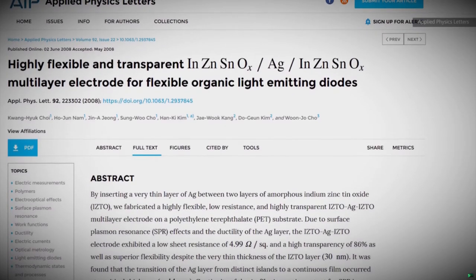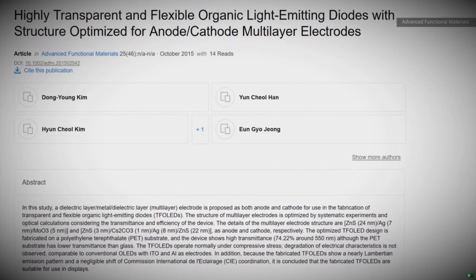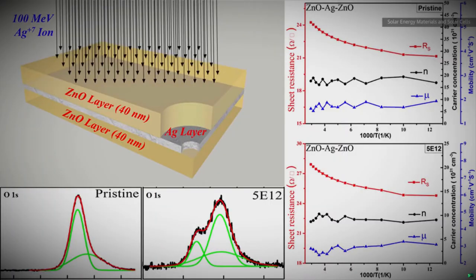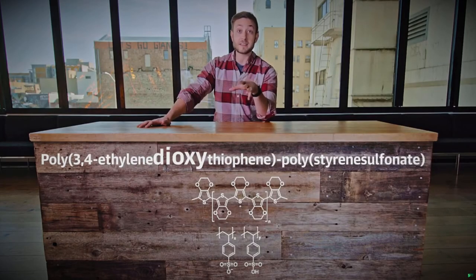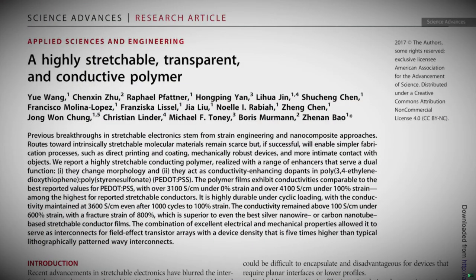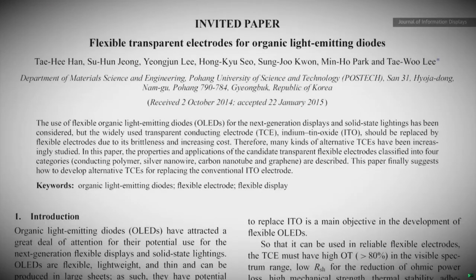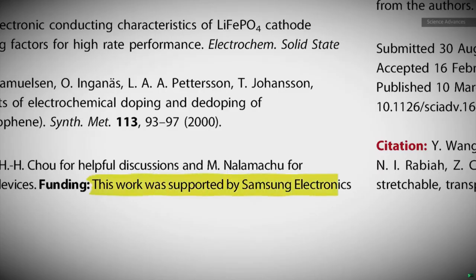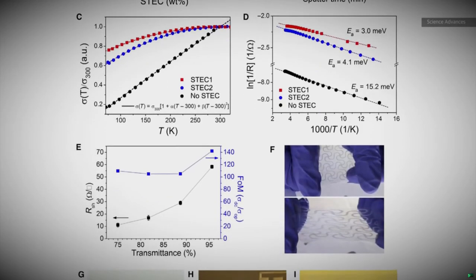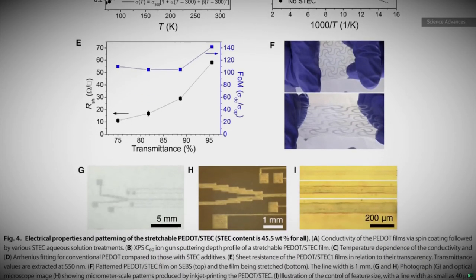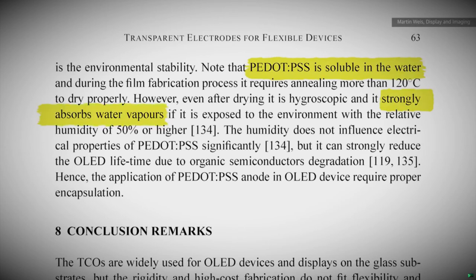In one candidate, a super thin layer of silver is sandwiched between two layers of either zinc sulfide or oxide. These layers are less than 50 nanometers thick, and they are remarkably transparent and stand up to repeated bending with no loss of performance. The other candidate is called PEDOT:PSS, or poly-3,4-ethylenedioxythiophene-polystyrene sulfonate. Researchers have been looking at it as a replacement for ITO for years, including a few studies that Samsung helped fund. PEDOT:PSS is a flexible, transparent, electrically conductive plastic, which seems like a great candidate for flexible OLEDs. One downside is that it loves water and absorbs it readily if humidity cracks 50%, so any OLED using this compound would need to be thoroughly encapsulated.